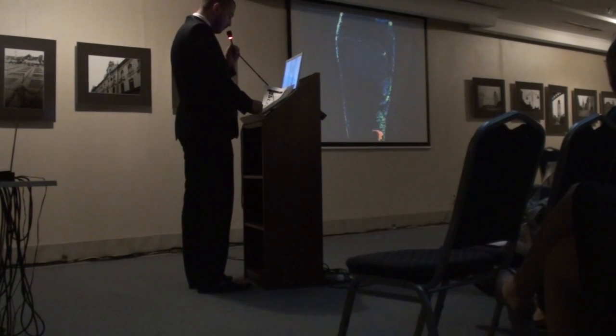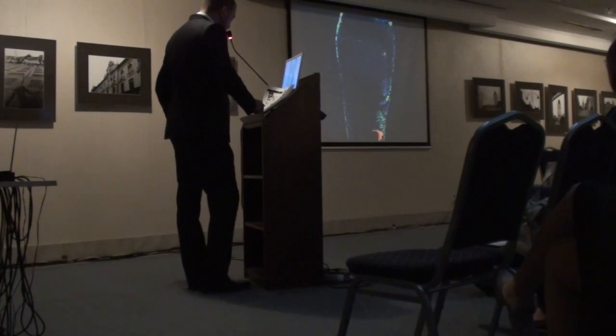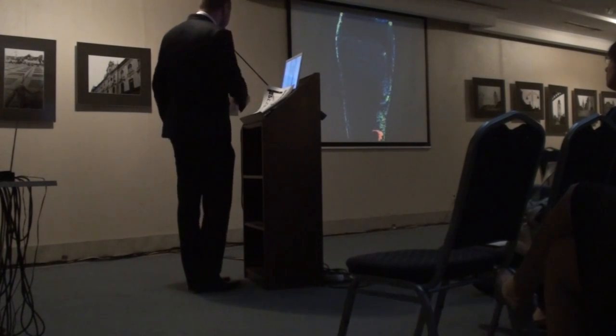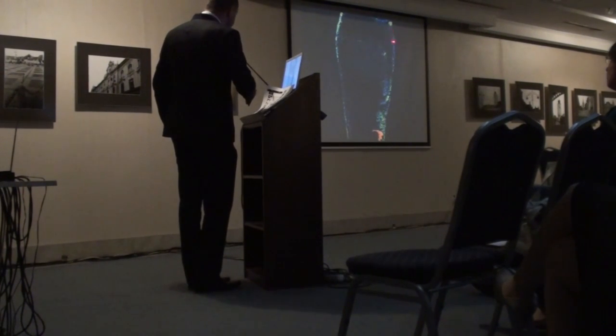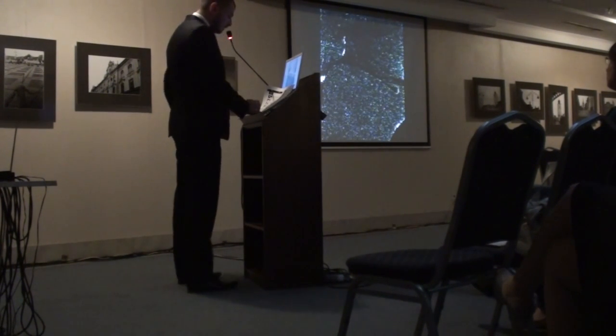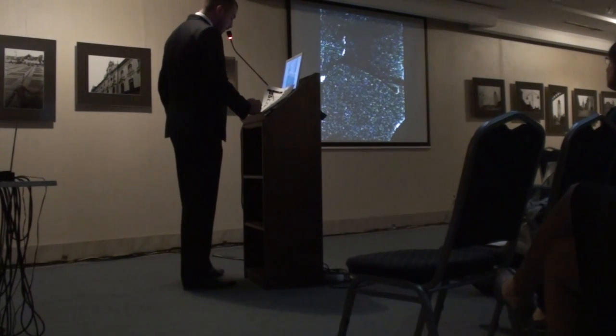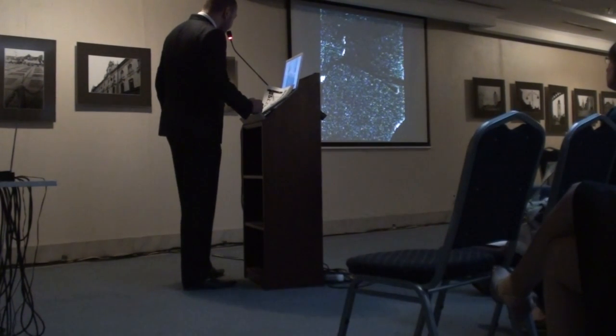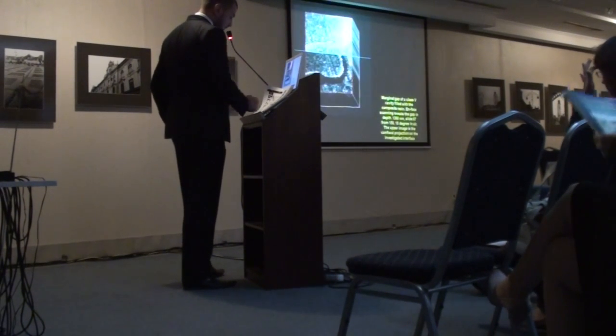Our research group did a lot of investigation on this topic, showing problems of marginal fitting on the resin composite fillings, such as in this picture, 0.78 millimeters inside the structure, along with material defects inside of the fillings. This image presents a poor marginal fitting of the filling together with a defect near. The possibility of this failure is greater in this case due to the defect situation.